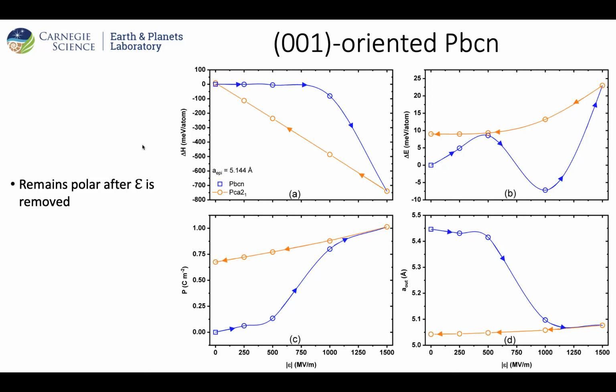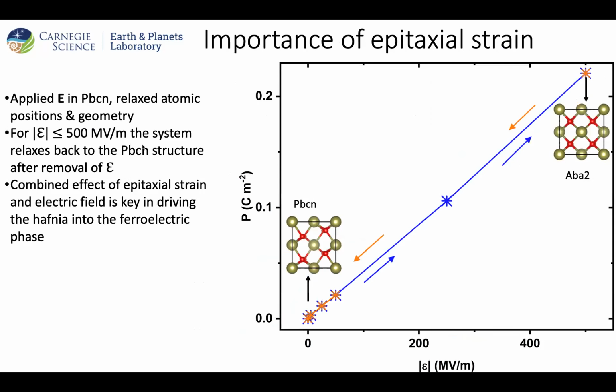Then we ask the question, what happens if you take off the strain, so just relax everything. We did so, and when you relax everything and still apply the electric field along the same direction, which is the crystallographic P here, then up until a reasonable, let's say 500 megavolt per meter, and then when you decrease the electric field, it goes back along the same path, back to the PBCN phase. So this tells us that key in stabilizing the ferroelectric phase in hafnia are the epitaxial strain and the electric field. It's their combined action that actually helps in the stabilization.